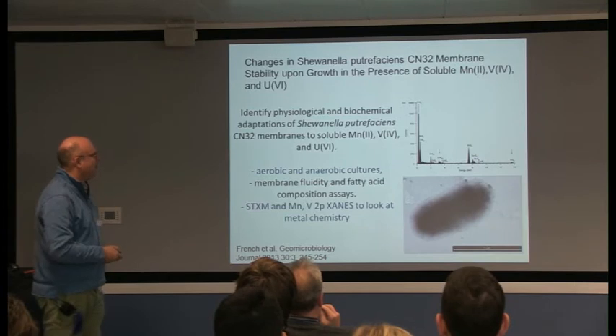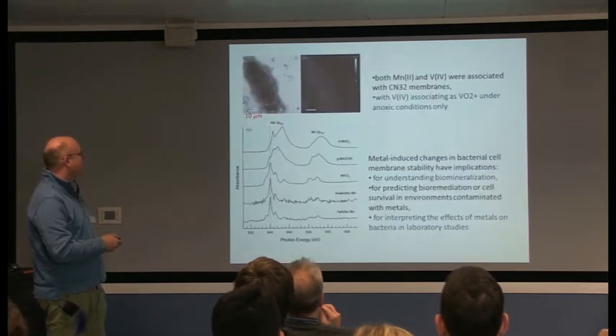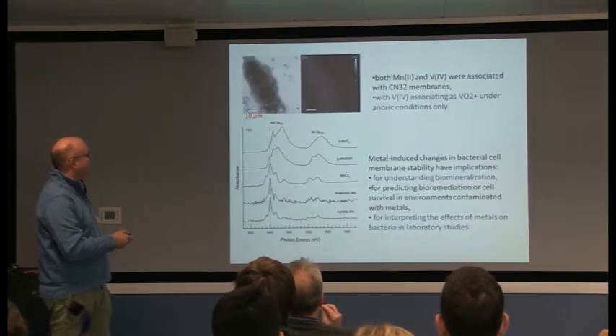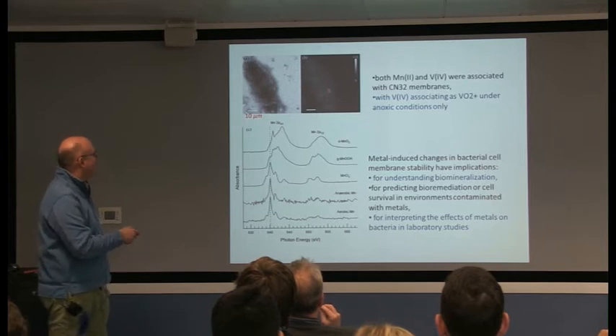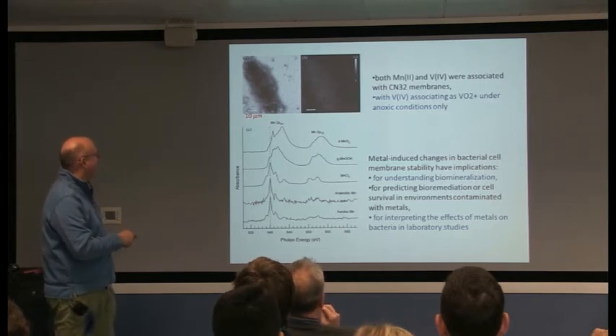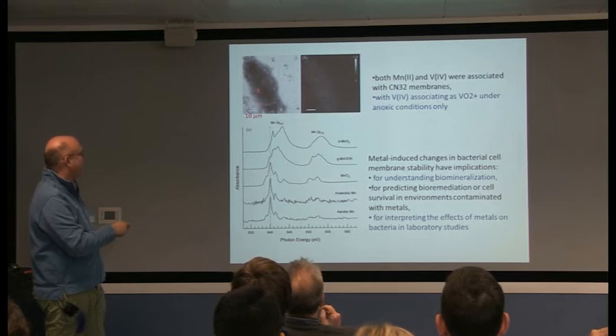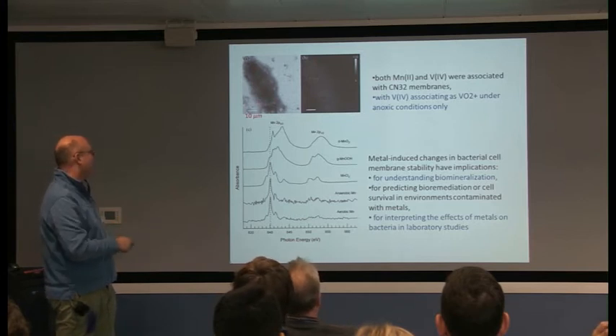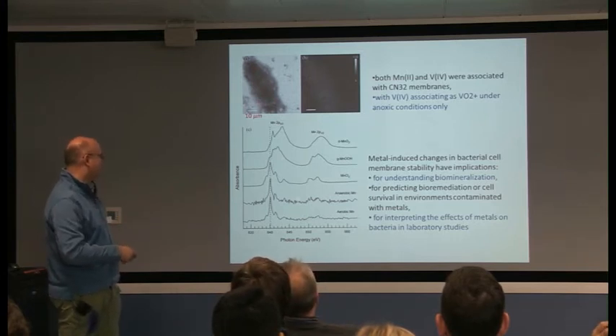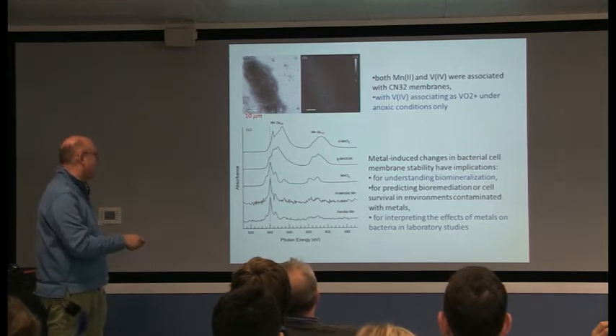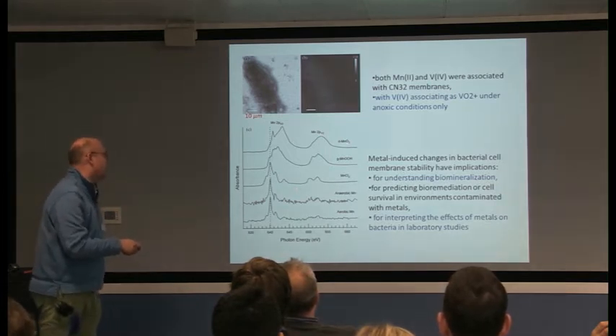You can see it's a micron big, so you need quite good resolution to study the edge of it. This is a manganese image, and that's the cell image, and you can see that manganese is associated with the cell quite closely. And if you do the spectroscopy, these are Mn4, Mn3, and Mn2.